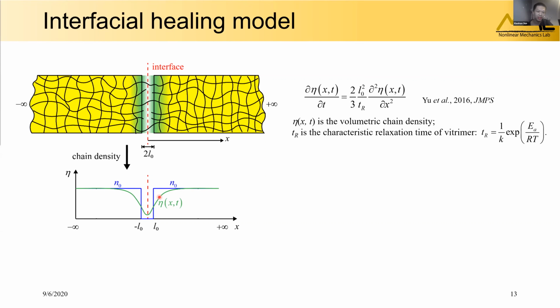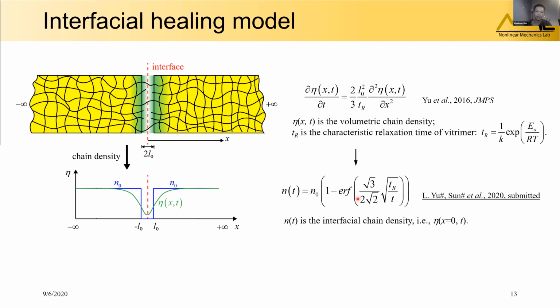The chain density is 0 inside the gap, the interface gap, and is a constant N0 outside this gap. Solving this equation using these boundary conditions, we can obtain the interfacial chain density in this formula. From the formula, we can see with the longer healing time t or the smaller τR, which corresponds to a higher temperature, the interfacial chain density is larger.